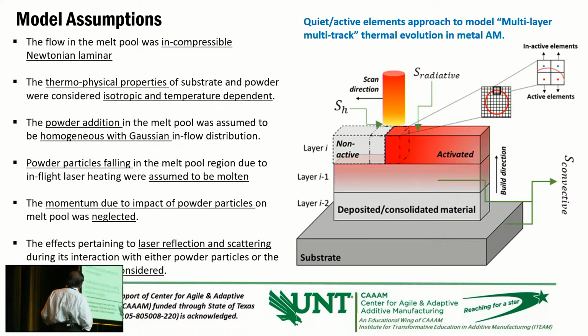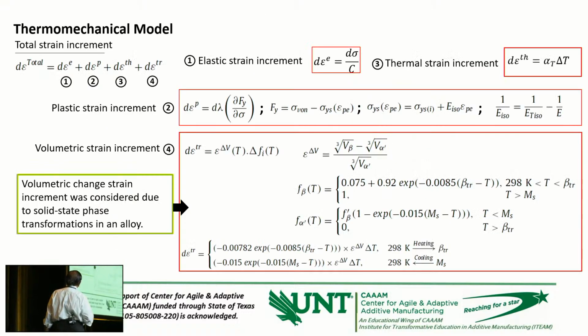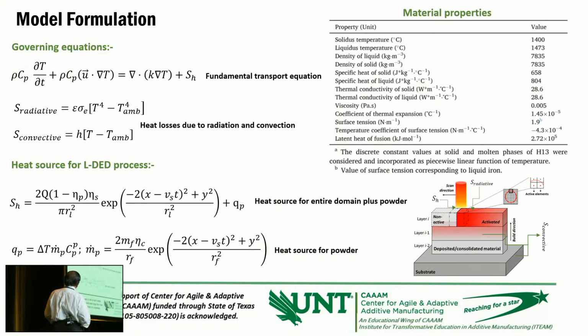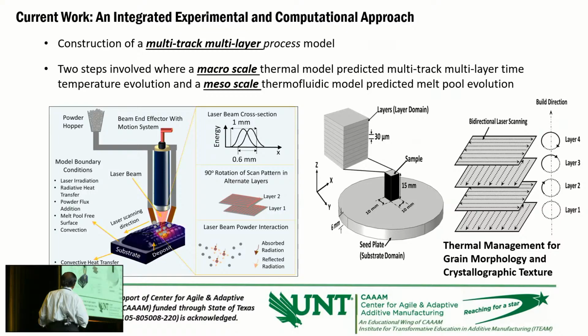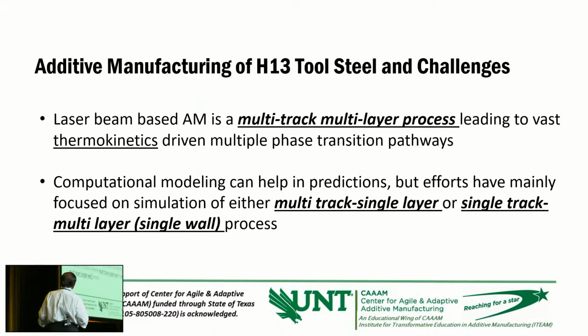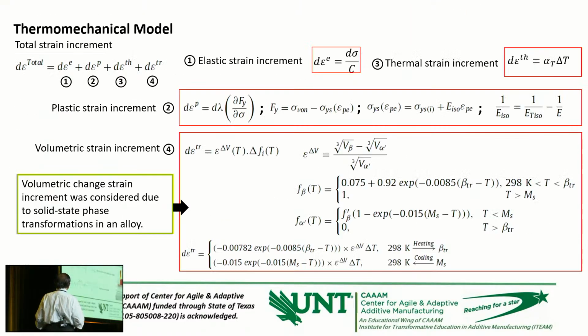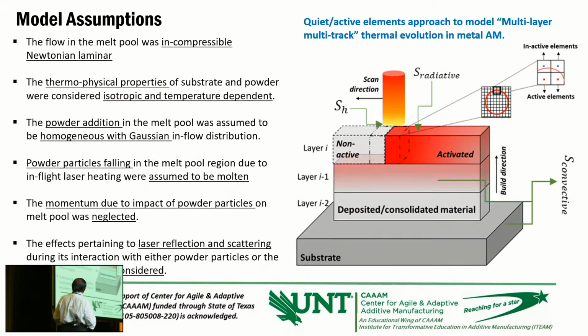Powder addition in the melt pool was assumed to be homogeneous with Gaussian flow distribution. That's why you see the earlier equation. Let me go back. Here also the Gaussian distribution. Powders are thrown into the laser beam, and the distribution of the powder flow is a Gaussian, which is given by this equation, same as this. This is the laser beam energy distribution in the laser beam, and both are Gaussian type. So that is what's considered in the model.